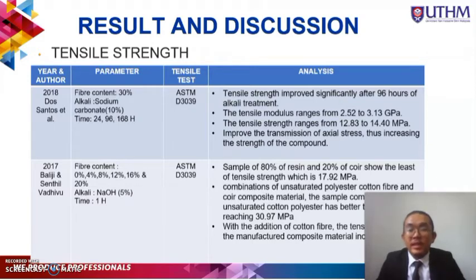Alright, in 2018, Dos Santos found that the tensile strength improved significantly after 96 hours of alkali treatment. The tensile modulus ranged from 2.52 to 3.13 GPa, and the strength ranged from 12.83 to 14.40 MPa. The improvement is due to the transmission of stress, thus increasing the strength of the composite.